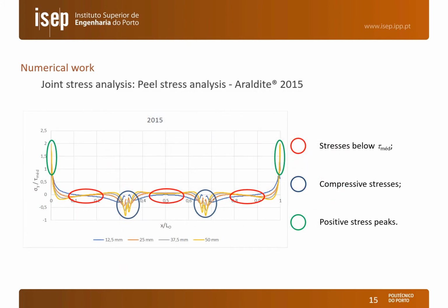We also performed a short stress analysis to try to understand how the stresses vary with the overlap length, and here we can see as an example the peel stresses for the Araldite 2015. We can see that we have major positive peak stresses at the overlap edges and compressive stresses in the middle at the edge of the middle step, and in most of the region in the middle of the steps we have nil or close to nil stresses. We can also see that the peak stresses tend to increase as we increase the overlap length, and this is why the joints with the AV138 could not get a high strength for big overlaps.